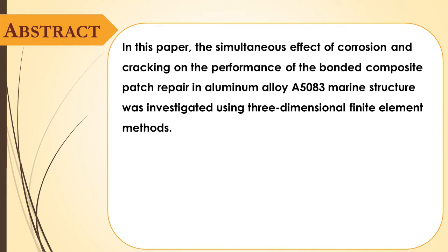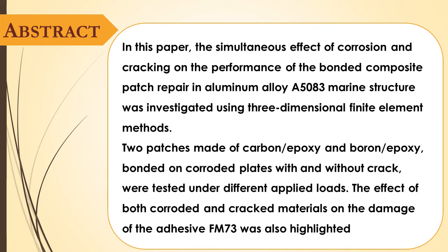aluminum alloy A5083 marine structure was investigated using three-dimensional finite element method. Two patches made of carbon epoxy and boron epoxy bonded on a corroded plate with and without crack were tested under different applied loads. The effect of both corroded and cracked materials on the damage of the adhesive FM73 was also highlighted.